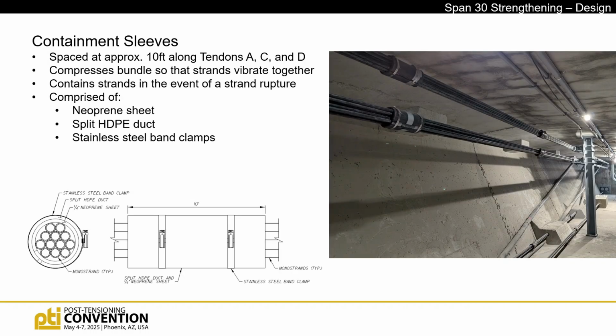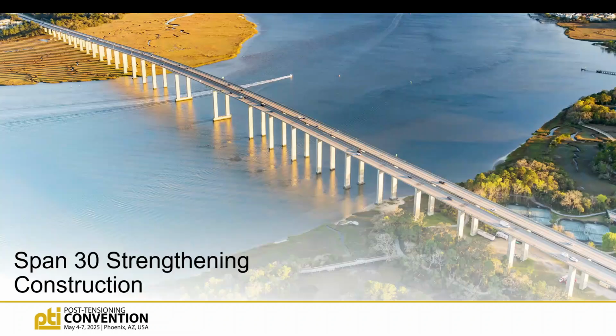And then because we've got unducted tendons, there were some concerns about the strands vibrating individually. And also, if a strand were to release, we didn't want it whipping around inside the bridge. So we used what we call containment sleeves, which are just a very rudimentary design. It's just a neoprene sheet wrapped in a split HDPE duct with stainless steel band clamps. They're spaced every 10 feet, plus or minus, along the length of the tendons. With that, I'll turn it back over to Jason to talk about the implementation of this.